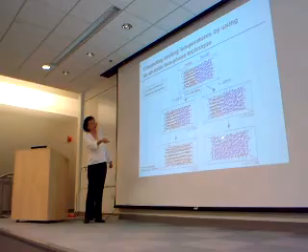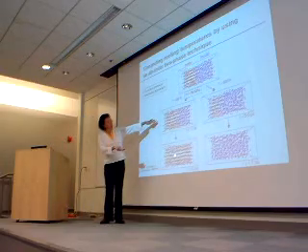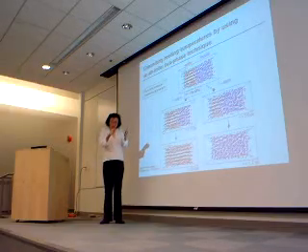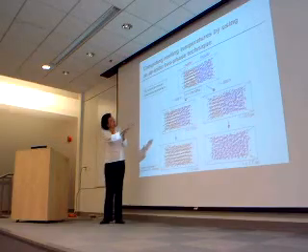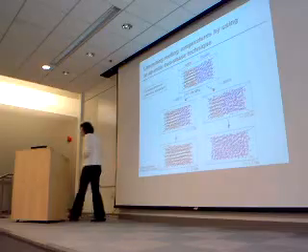We do this for another temperature. And we have identified a situation where here we have the solid, which is more stable, and here we have the liquid. And then we go and do the same simulation in between 800 and 900 K. And then finally we get to bracket the melting temperature of the system.